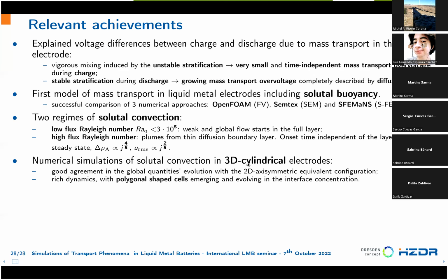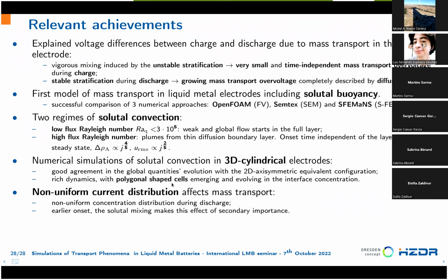We also study solutal convection in 3D electrodes, and we see that they agree very well with 2D axisymmetric, but the dynamics is not at all axisymmetric. We have very nice plumes and polygonal shaped cells evolving at the interface. We also show that in reality, in liquid metal batteries, in application, the current distribution is not uniform at the positive electrode electrolyte interface, but this affects mostly discharge, and solutal convection in charge makes the effect of non-uniform current distribution secondary.